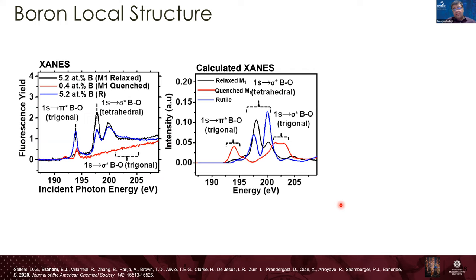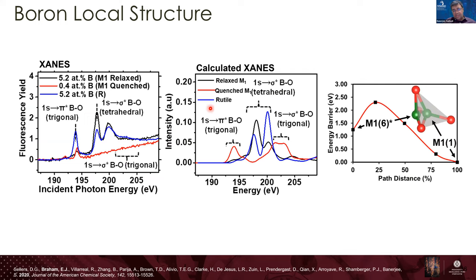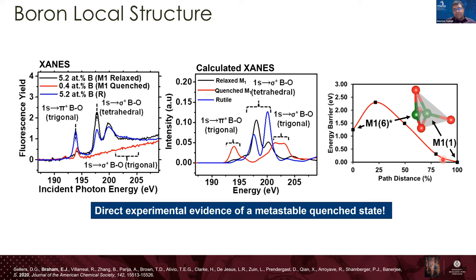And so again, we've done a lot of soft X-ray measurements. This is at the CLS, where we were able to look at the boron local environment, and when you cool it down, it's stuck in this unfavorable three coordinate site, and then it relaxes to an approximately tetrahedral site over a period of time. And so really, this is super interesting because boron definitely then is a real clock.